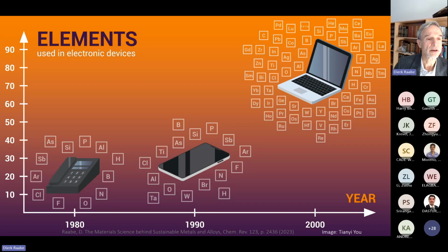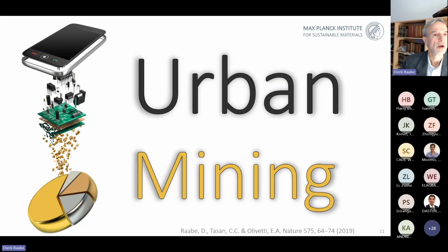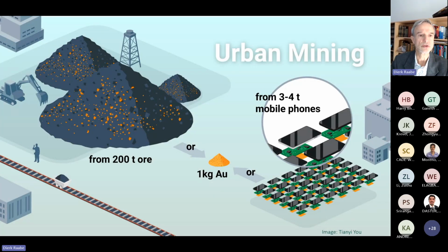This is, I think, an endeavor, a quest that we are only about to begin, and the recycling quotas in the moment in this field are really tiny, practically negligible. And there's a lot to do, an area that is coined or called urban mining. Just to give you a rough flavor of what that translates to, we can get from the best South African mines up to 1 kilogram of gold, for instance, from 200 tons of mineral. And we can get the same amount of gold when we extract it from 3 to 4 tons of mobile phones, essentially from the chips there, of course. And that applies to the other metals also. So we have very, very rich urban sources, but how to extract them in a smart way is yet to be explored in high detail.